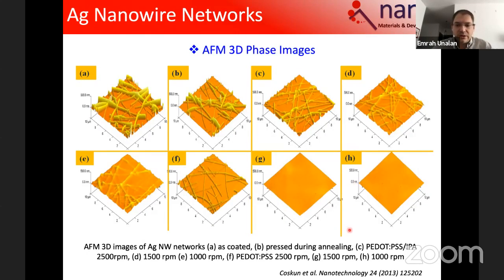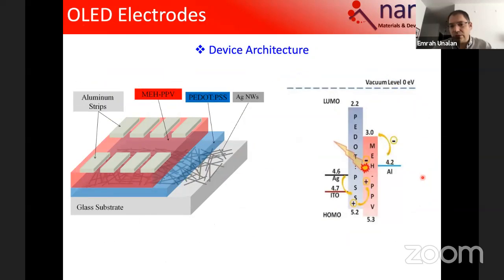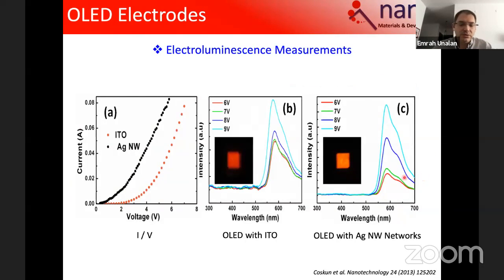So what Dr. Coşkun did was to change the PEDOT:PSS concentration and play around with the spin coating parameters, as you see, to planarize the film that we deposit on top of the silver nanowires. And voila, the result is, as you see, this is a control sample made with the ITO, and this is the control sample made with the silver nanowire networks. And this was, let me assure you, one of the first OLED papers dealing with silver nanowires back in 2013.